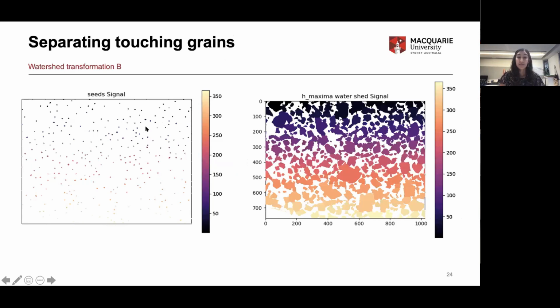So first we can apply seeds once we've identified the center of those grains. Now we know the distance to our nearest neighbor, we can cut along those grain boundaries. And it's also at this point where we automatically assign every single grain that we've detected a unique label or number so that we can refer back to it when we start thinking about grain size and being able to identify the grains in our data frame tables.